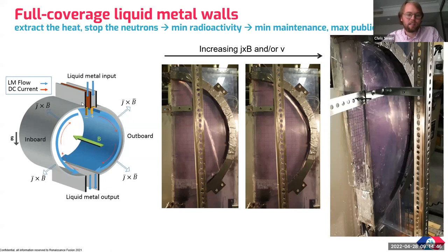This is a simplified cartoon here, but one of the processes that we're also patenting is not just stabilization by two current leads, one at the top and one at the bottom. We can actually put different voltages at different locations in the liquid metal film, and thereby induce local currents that push the film so that we get a homogeneous thickness. We're still working this out, but there are ways. It's not just going to be inhomogeneous. We have ways of controlling the liquid metal over the entire surface, even with 3D magnetic fields.